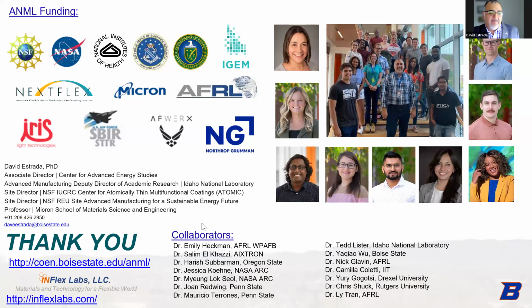We're focused now on improving the growth a little bit before going into the device applications. Regarding the use of the tool, things that caught us by surprise were the amount of nitrogen and hydrogen that were required, one, to dry the lines to the critical dew point before you're able to qualify the system. At one point, we calculated we'd have to swap out 50 hydrogen cylinders to meet the flows. And when you break that line, you might introduce more moisture. Luckily we're pretty dry here in Idaho. You're not as dry in State College. So if you break that hydrogen line, you might reduce your dew point again and then have to start over. So really understanding how much nitrogen you need and how much hydrogen you need is key.